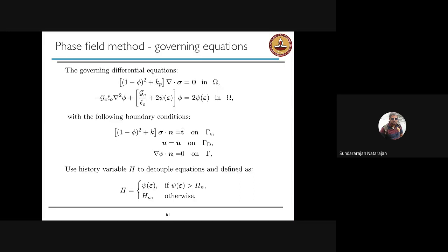You know, the first equation is very similar, if you ignore the factor, to the elasticity equation. So this equation is supplemented with a diffusion type equation, which is given by the second equation. Gc is the fracture toughness, and l0 is the phase field internal length, which helps us model the crack. Remember, the smaller the value, the sharper the cracks. And this is supplemented with boundary conditions as before.